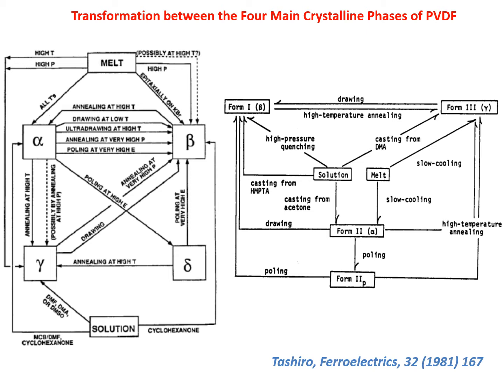You can anneal at high temperature. You can make mechanical stretching from alpha to beta. You can do some annealing at very high pressure and apply a very high electric field. So obviously from the melt, it's possible also to get the beta phase, or if you fail this protocol, you can lead from alpha phase to gamma phase or delta phase. So this was developed, let's say, 30 years ago, and then Tashiro also revisited this process and applied some different treatments in order to obtain basically some beta phase, either from the melt form or from the solution.